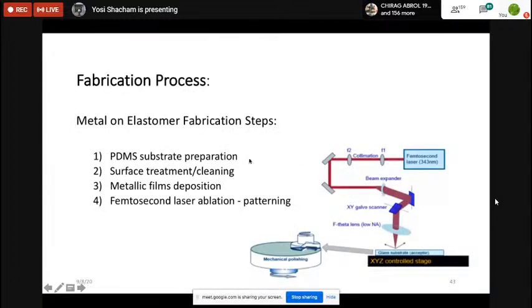First, one of the technologies which is very promising now, and many people are doing it, and we bought this system a few years ago. We are taking a laser, and this is a femtosecond laser. We're using the 343 nanometer wavelength, which is ultraviolet. We're using pulses of approximately 270 femtoseconds. We have a galvo scanner, so we can scan with the beam. First we prepare the substrate, then we do surface treatment and cleaning, then we put the metal, and then the laser beam is ablating the metal.